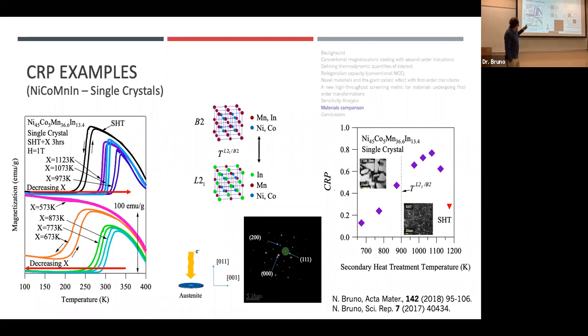I've also used this in studying nickel, cobalt, manganese, indium. These materials were all single crystals, and they exhibited different long-range order depending on what thermal treatment I was exposing it to. So I could do a secondary annealing treatment below 900 Kelvin, and I would grow or stabilize an L21 phase. The atoms would be arranged a certain way. And I looked at that microstructure with dark field imaging from transmission electron microscopy. And I found that for some reason, the B2 phase, B2 long-range order in these materials gives a much higher CRP. So it's interesting because you can have one composition and you have a wide range of CRP depending on what the microstructure is and the long-range order.